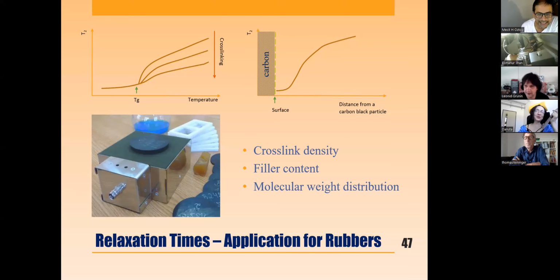Did you try to measure diffusion coefficient in some solid systems using your equipment? Well, diffusion. If you have something like starch or cellulose and you have water inside, you can look at diffusion of water. So this is definitely possible, and we can estimate the requirements for the pulse gradient in these systems. But the self-diffusion of solids is not something that we are targeting in our hardware, because this is an absolutely different device with a strong gradient. Okay. So now clear.